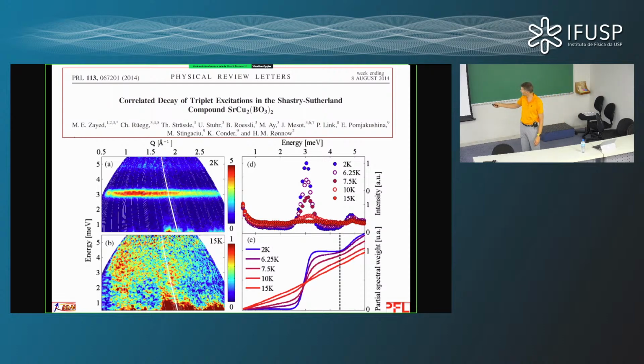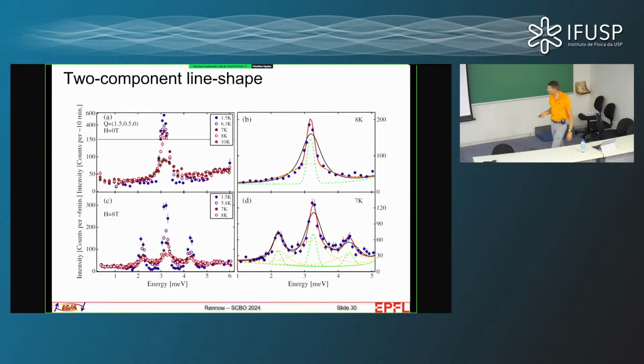Now, the peculiar thing is that it actually happens much earlier. You can see here already at 6 Kelvin, I've reduced dramatically. 7 Kelvin, half of the intensity is gone. 10 Kelvin, it's almost completely smeared out. So it happens much faster than we would expect based on just measuring the size of the gap. And so we made this observation. We looked a little bit more carefully into this.